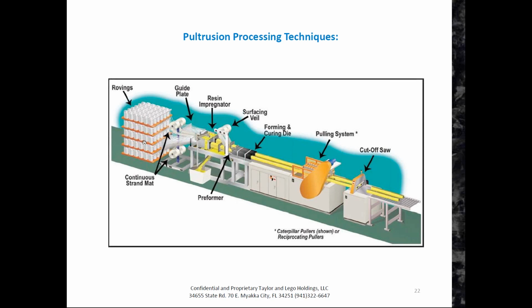These are creels right here of glass fiber, and those creels get pulled in close proximity to one another through an impregnator here that impregnates it with resin. Usually it's epoxy, sometimes it's vinyl ester, and then as it pulls from the very end of this machine, it goes through a forming die and basically forms the structure into a linear shape that then gets chopped off.